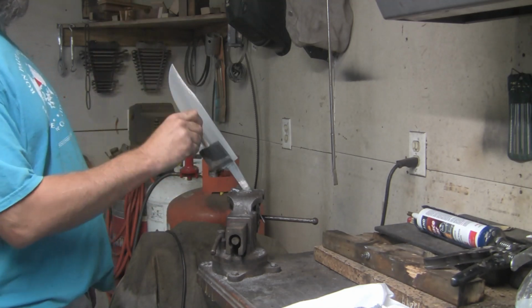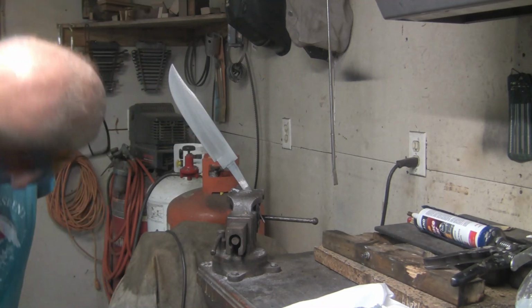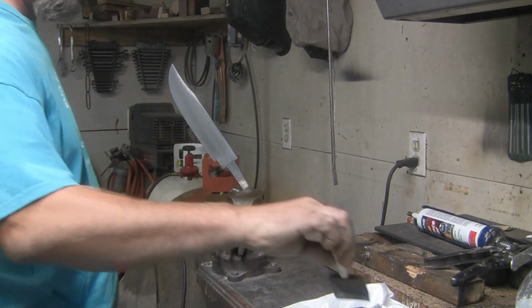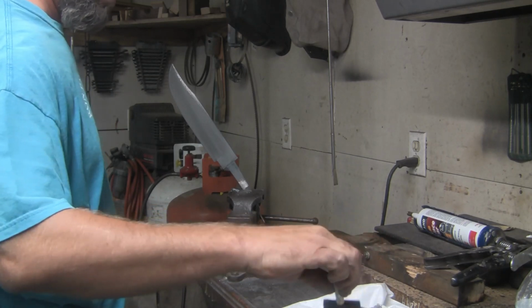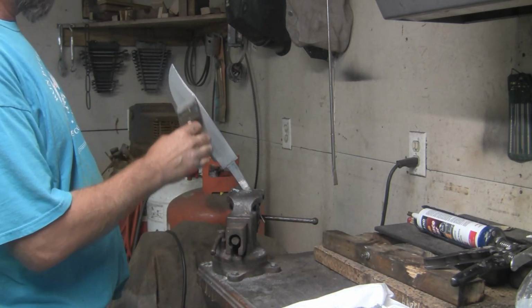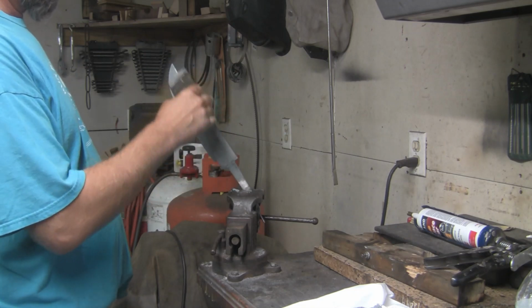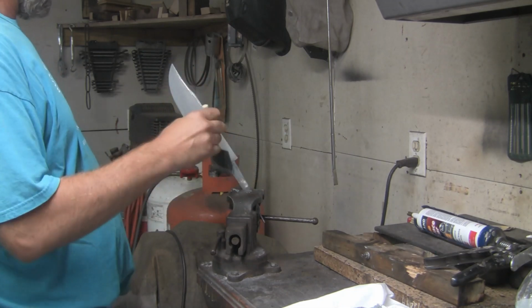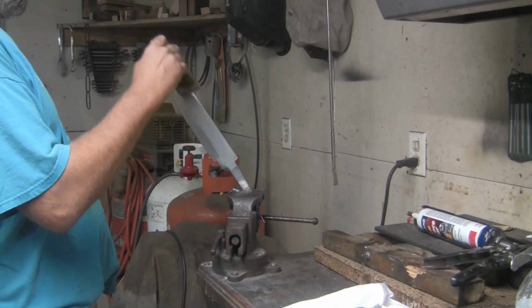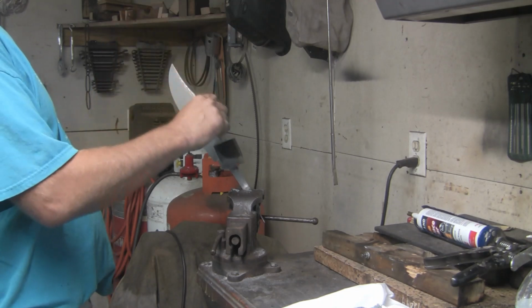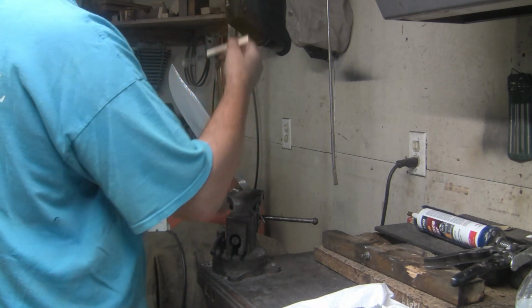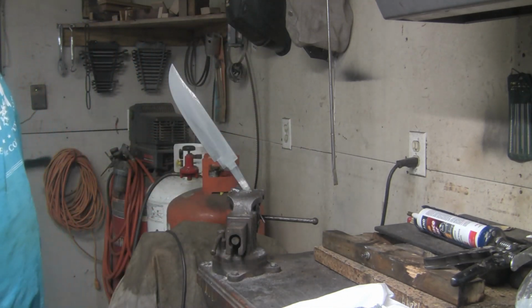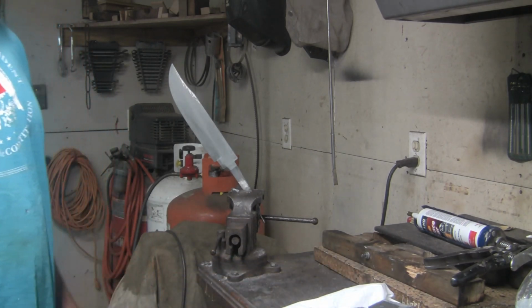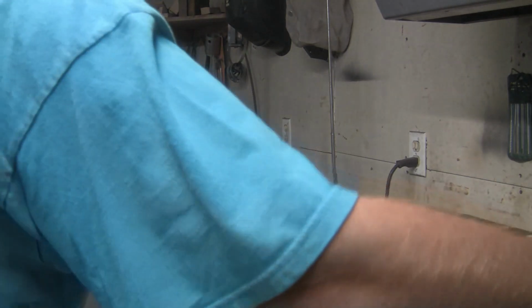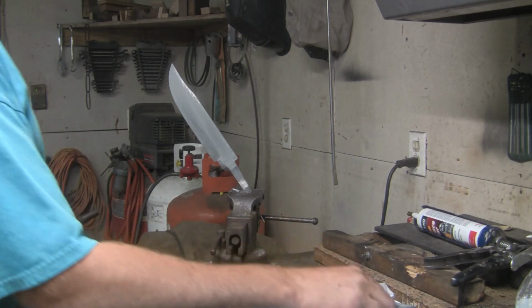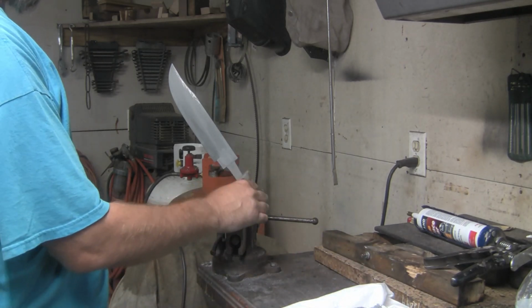So this is more than likely going to be an all-day process because this is going to have to dry, and it's going to have to dry, you know, all the way. I do have the smoker going, so after I get everything applied, I might just take it over to the smoker, get it close to that. That runs around 250 degrees, and then just let it kind of cure from there.